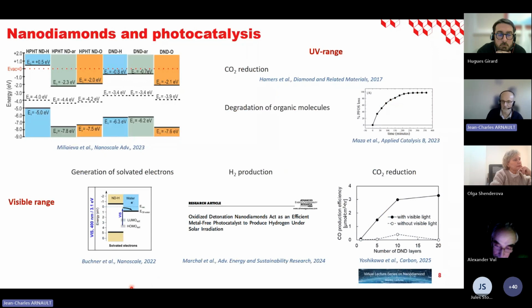What about the visible? If we look at the recent literature, we can see some studies that suggest that nanodiamond can be active in the visible range. The first one was using hydrogenated detonation nanodiamonds in the visible range, at 400 nanometers. This study showed that this nanodiamond can generate solvated electrons in the visible range. According to the authors, this could be related to sp2 carbon present in the particles or even defects. Then for hydrogen production, we reported, this is our group work together with Strasbourg, hydrogen production using oxidized detonation nanodiamond under solar irradiation. And very recently, last year, a Japanese group showed that CO2 reduction can be achieved if they use detonation nanodiamonds with a high nitrogen content.